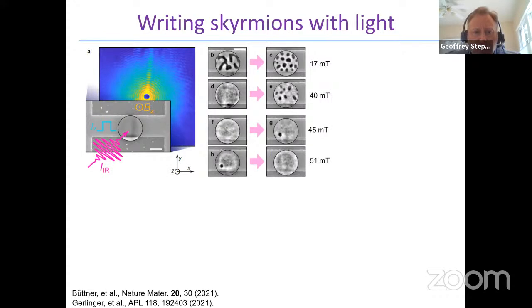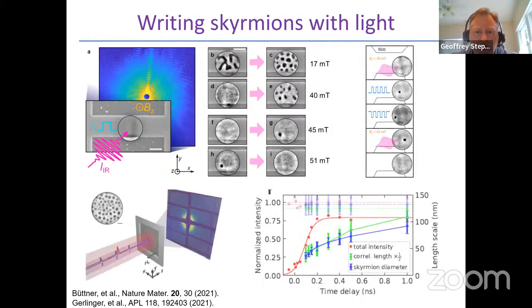Several groups, including our own, have shown recently that in ferromagnetic multilayer stacks, ultra-fast femtosecond laser pulses can be used to generate either groups of magnetic skyrmions or individual skyrmions, and can do so in racetrack devices to allow for the ultra-fast creation, translation, and annihilation of magnetic skyrmions in devices. So there's been a tremendous amount of progress since the discovery of interfacial DMI in the engineering of ferromagnetic stacks with dissimilar interfaces to generate these kinds of chiral textures and to generate the kinds of conditions that allow for their manipulation in potential racetrack devices or other logic devices for applications.